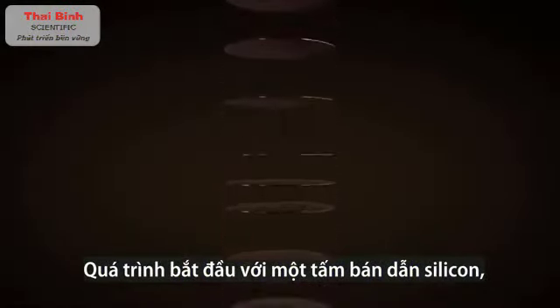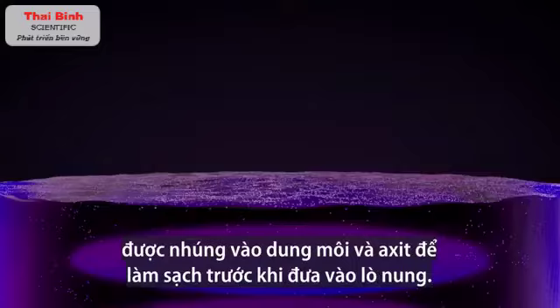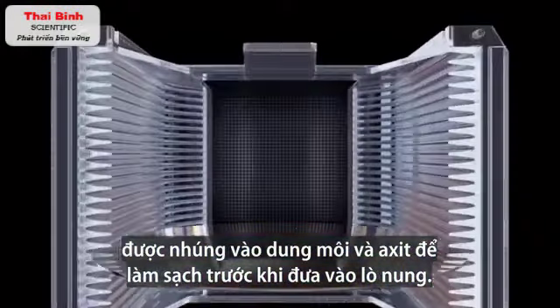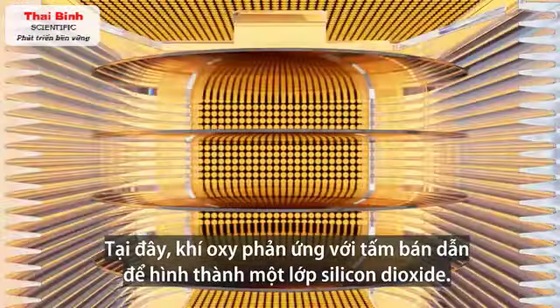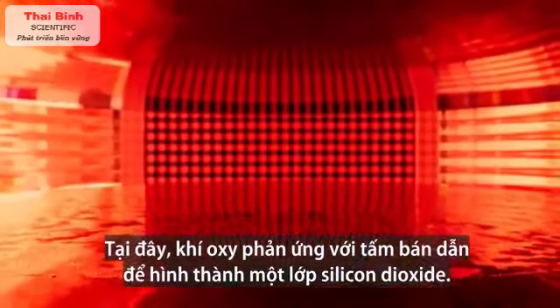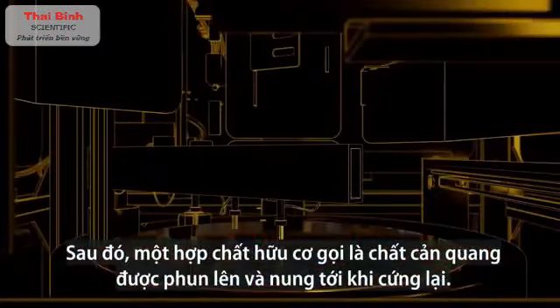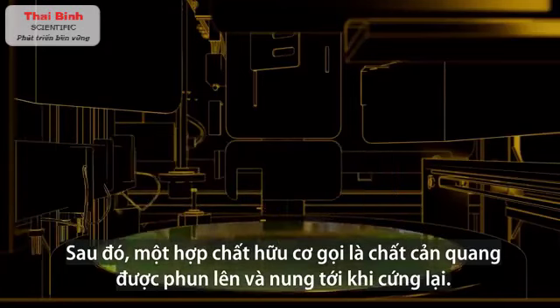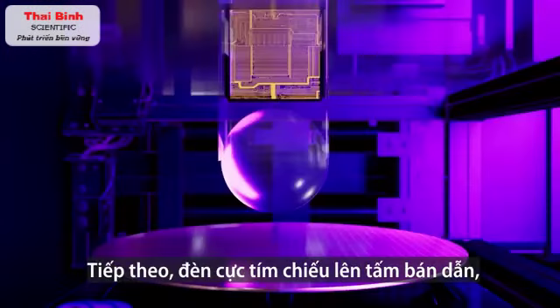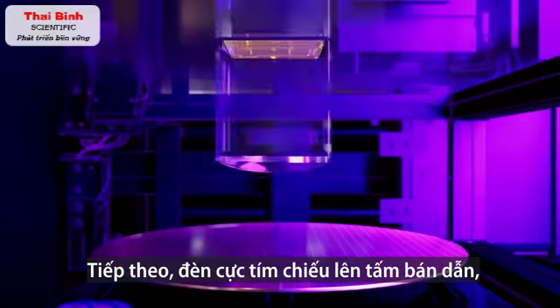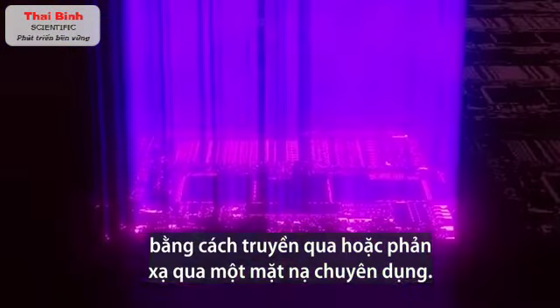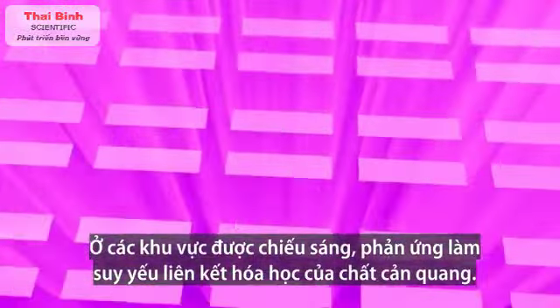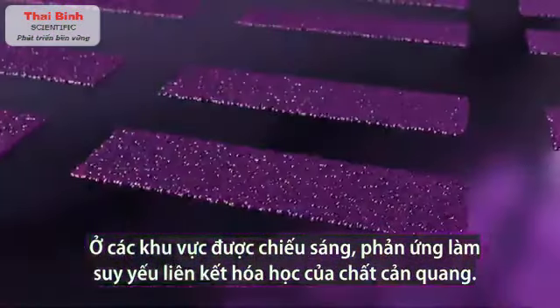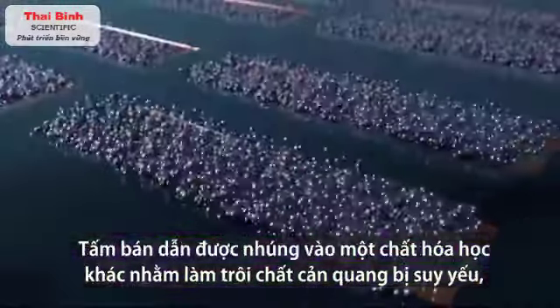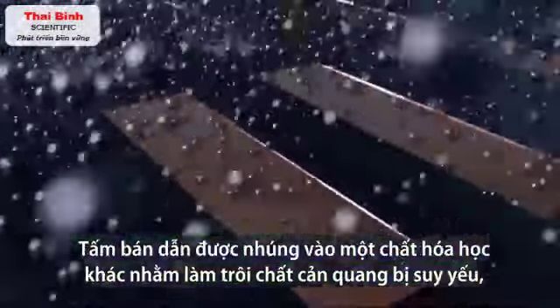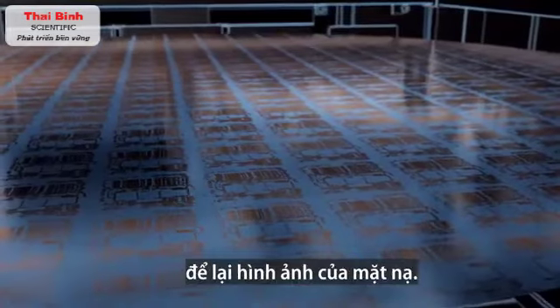The process starts with a wafer of silicon, which is doused in solvents and acids to strip it clean before entering a furnace. Here, oxygen gas reacts with the wafer to form a layer of silicon dioxide. Then a liquid called photoresist is spun on and baked to harden. Next, ultraviolet light selectively illuminates the wafer by passing through or reflecting off a specialized mask. In the lit areas, a reaction weakens the photoresist's chemical bonds. The wafer is doused in another chemical to wash away that weakened photoresist, leaving an image of the mask.